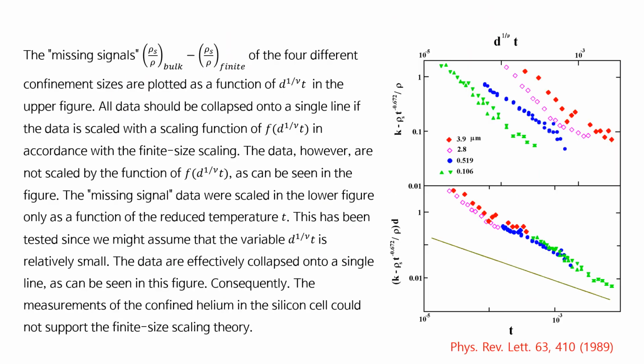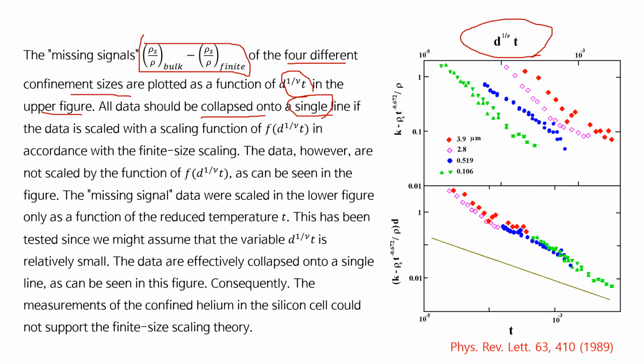The missing signal, this value of the four different confined sizes, are plotted as a function of d to the 1 over nu t in the upper figure to test the finite size scaling theory. All data should be collapsed onto a single line if the data is scaled with a scaling function of this function in accordance with the finite size scaling.